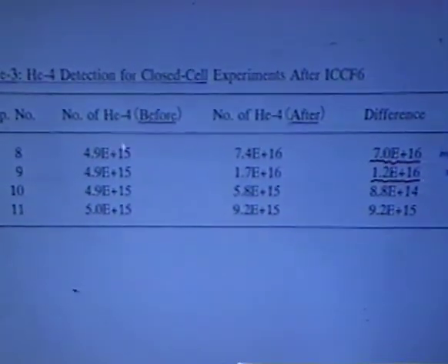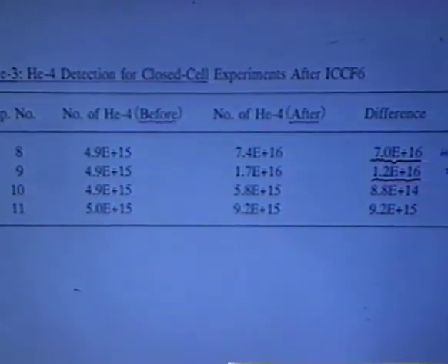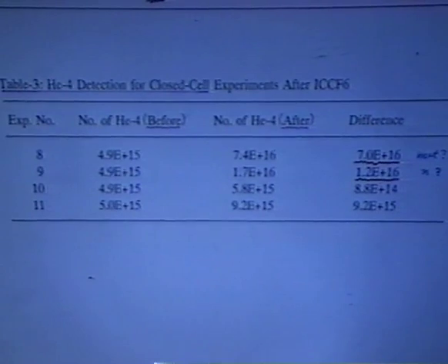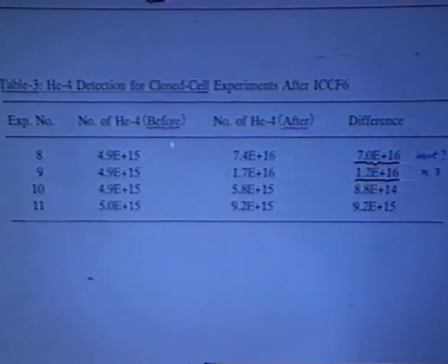Let me show the example of helium analysis for the latest 4 experiments after we improved the mass spectrometer. We are comparing here the helium atom numbers before and after electrolysis. Before electrolysis, we have about 10 to the 15th atoms in the upper room of the cell. After the experiment, in this case, it increased 15 times or so. It's a net increase. In this case, we don't see very clear excess heat. However, it was a very long run, about 720 hours. So we might have very slight excess heat accumulated for a very long time. We are not very sure about this.